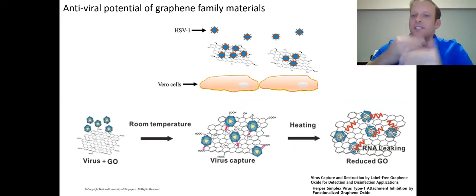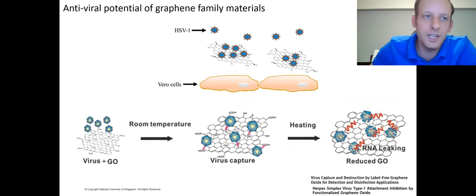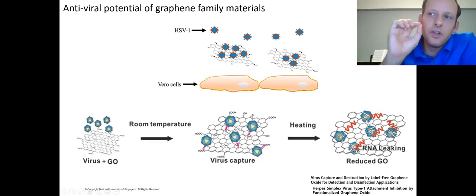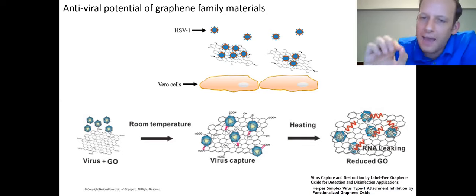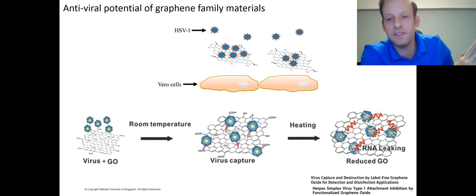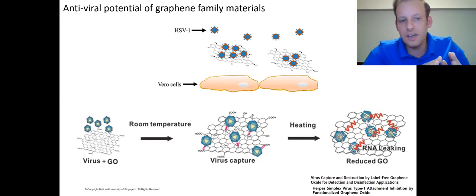So if you think about this type of strategy here on the screen, the second strategy, this paper has shown that if you bind a virus particle to graphene oxide at a relatively low temperature, you're able to break 5 times more membranes compared to the same temperature without graphene. So in a very